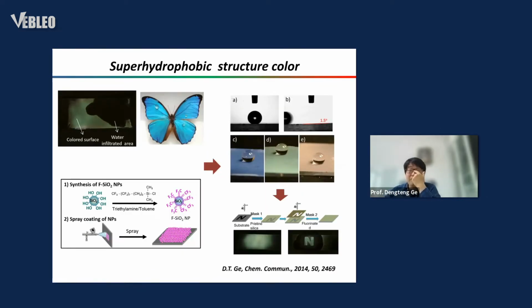Another question is that when we make the uniform structure colors, we found that if a drop of water is on the surface, water can infiltrate the pores, so the structure color disappears. So can we make a structure color with superhydrophobicity, similar to the morpho butterfly? To solve this problem, we modify the silicon nanoparticle with the fluorinated silane. Then coating on the surface, we can generate a superhydrophobic surface with structure colors.